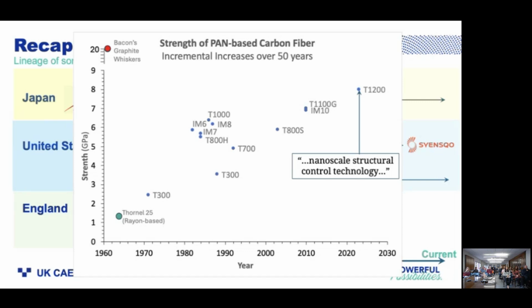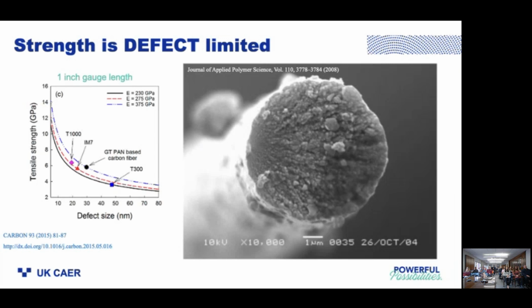So we still have room to advance carbon fiber, but reaching a tensile strength of 8 gigapascal is pretty remarkable. It's really limited by the defects on those fibers. You can see in this SEM picture that there's a point here and a chevron pattern radiating out of that fiber. All of these fibers in tension fail from some defect present on the surface, or perhaps some void or inclusion interior to the filament, but particularly on the surface.